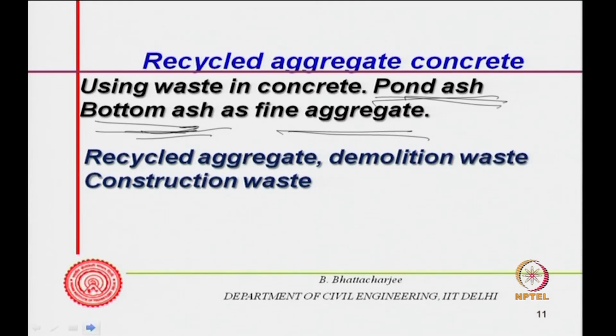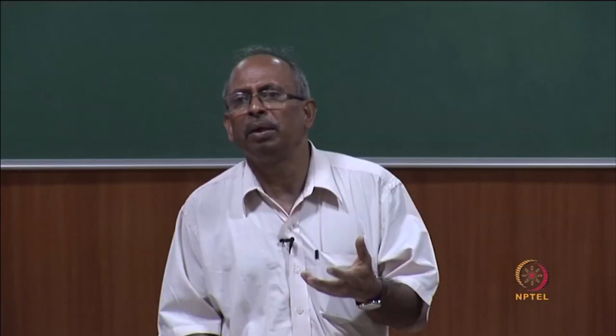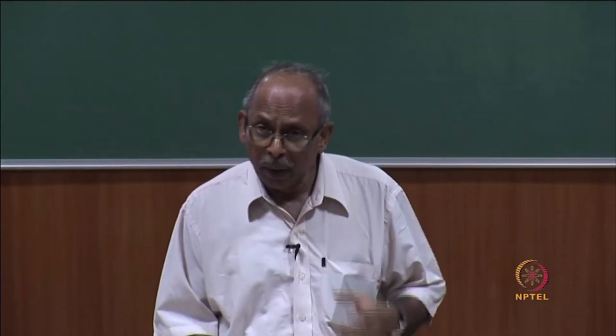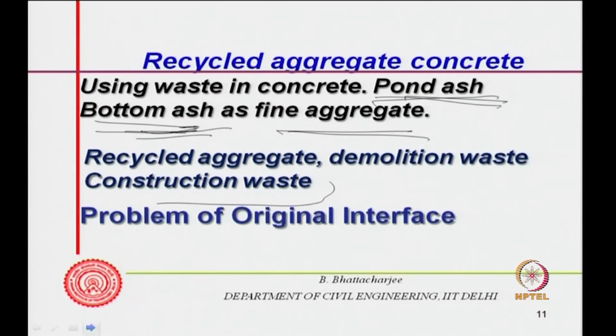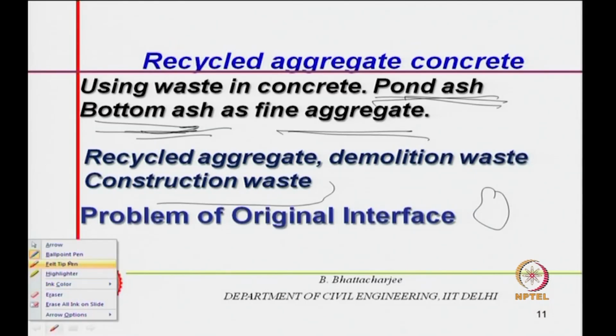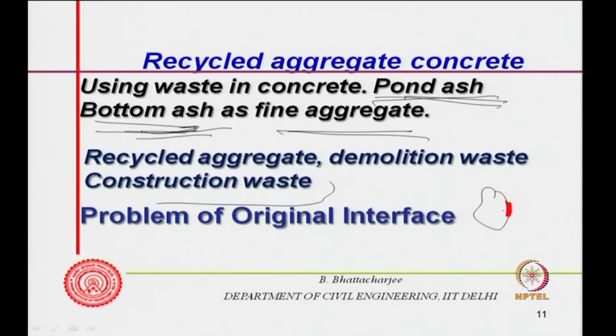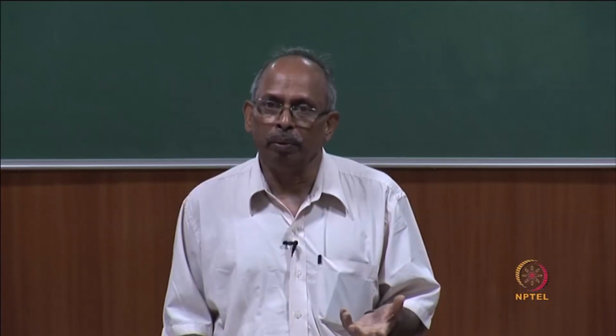Recycled aggregate, demolition waste, construction waste, they have to be crushed and made into aggregate. These are in the research stage, still have to be used, but these are possibilities. People are attempting them. One problem associated with this is, whenever you crush recycled aggregate, you will have an original mortar layer adhering to it. The original interface remains. So, when you now add new, fresh mortar, they would again form an interfacial transition zone. So, the original interface remains, and people are trying to solve this.